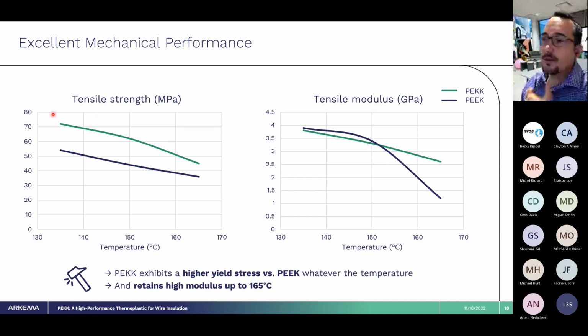And what you can see, due to the extra ketone in the polymer and that higher TG, is a higher tensile strength at temperatures. So at temperatures of 130 to 160 degrees C, you're seeing a higher tensile strength for the PEKK material. So for these extreme applications we're talking about, you're going to have a higher strength.